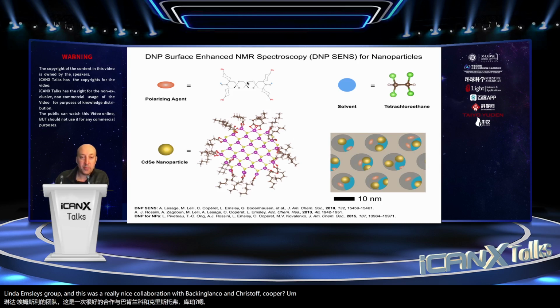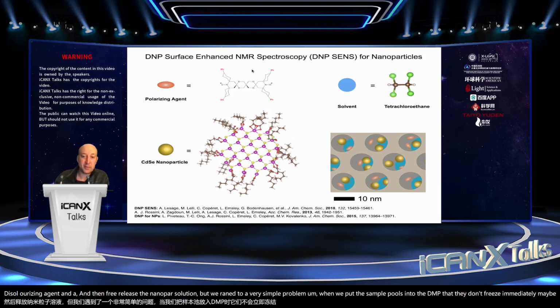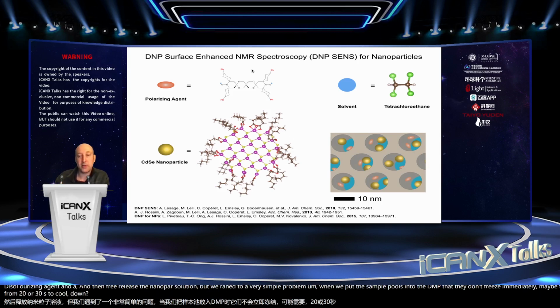So Maxim and Christophe came up with the idea of how we're going to do DNP on a nanoparticle. The first thing we actually tried to do was just take a colloidal nanoparticle solution, dissolve our polarizing agent in it, and then freeze the nanoparticle solution. But we ran into a very simple problem. When we put the samples into the DNP, they don't freeze immediately. Maybe takes them 20 or 30 seconds to cool down to 100 Kelvin.